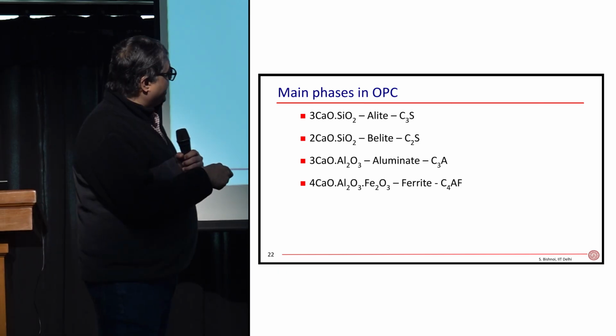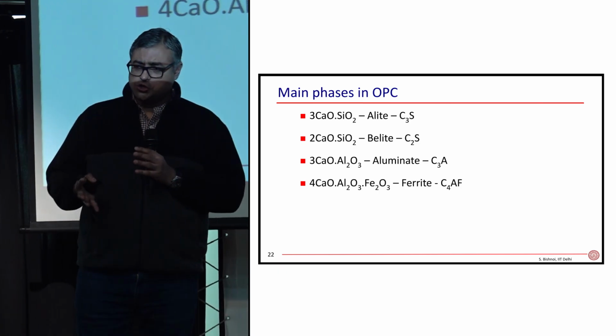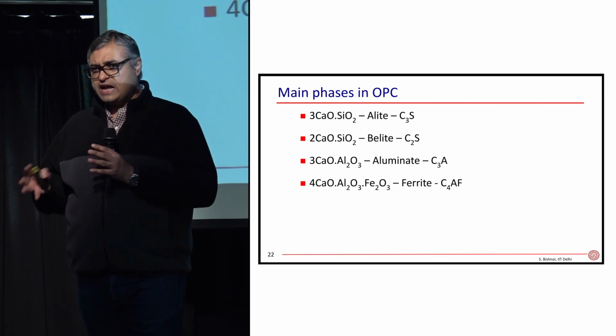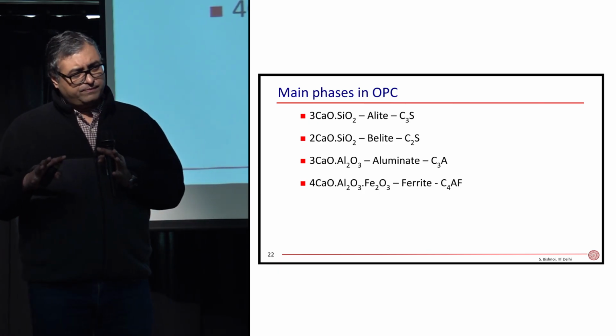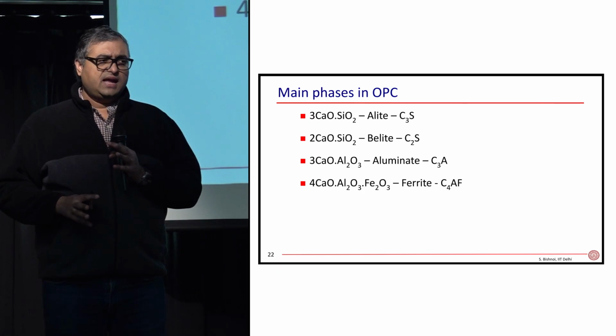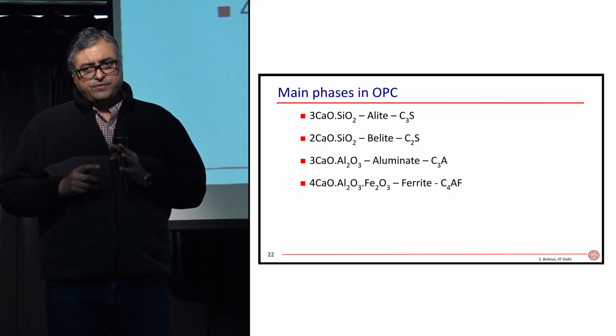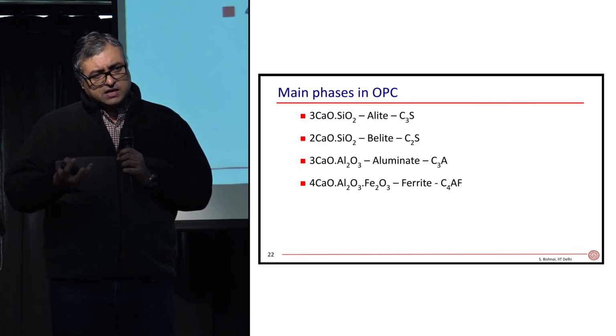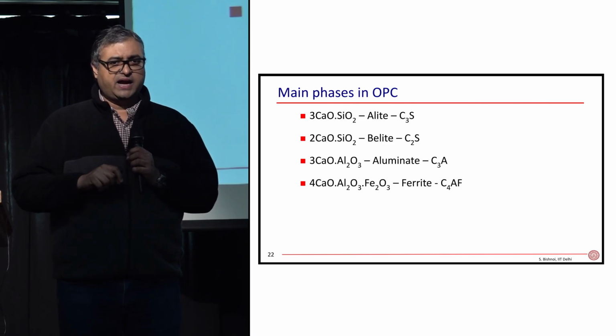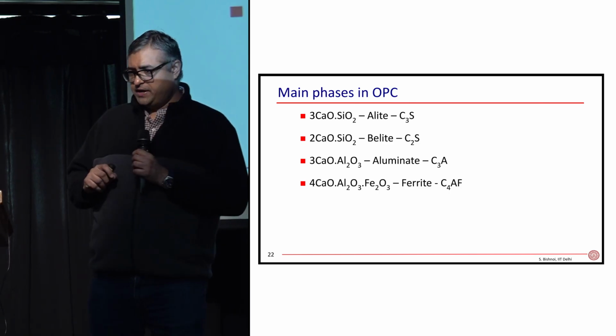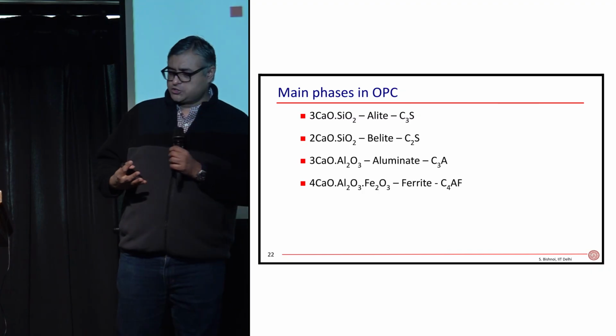And then there is ferrite, which is a solid solution of calcium aluminate with some iron in there. In that solid solution, if you put it in water, the calcium part is able to leach out, leaving the iron behind — we'll talk about that in a minute. But although we write those reactions in a stoichiometric way, that's not really what is happening.